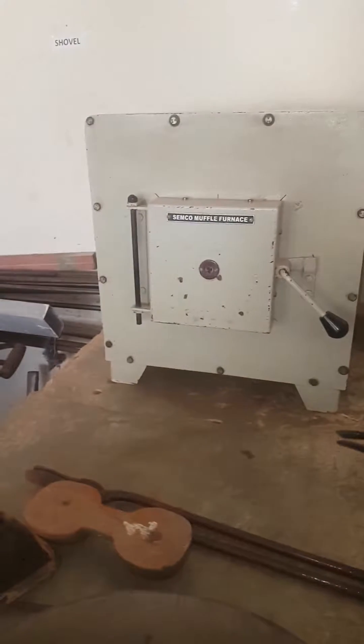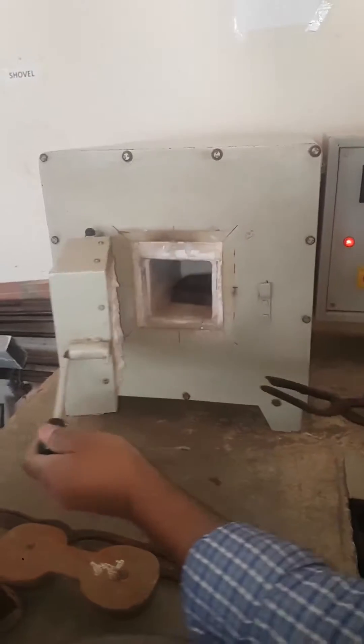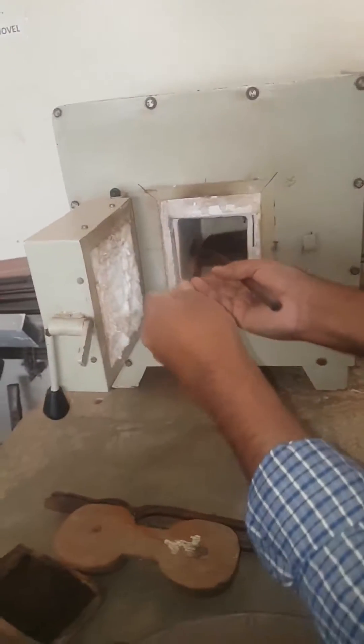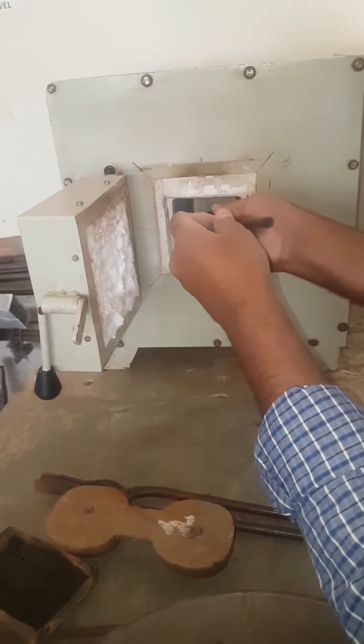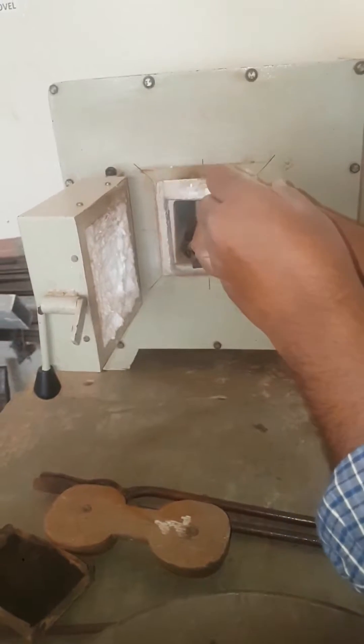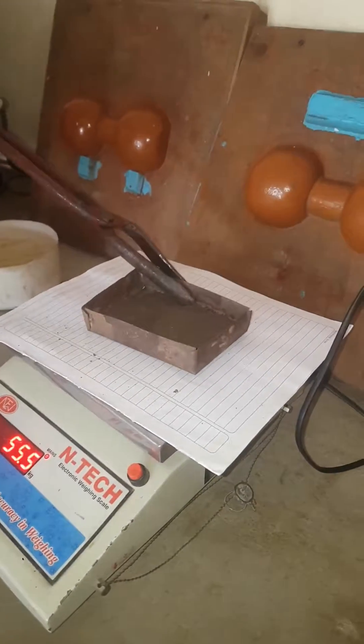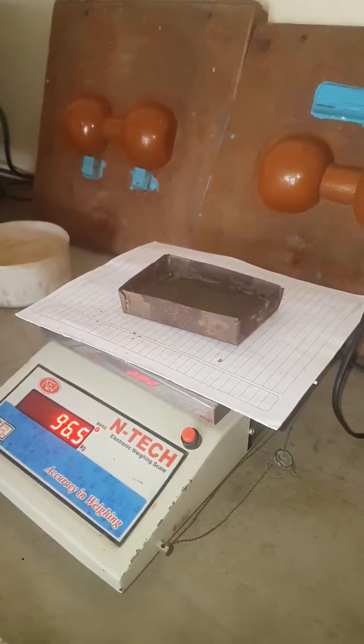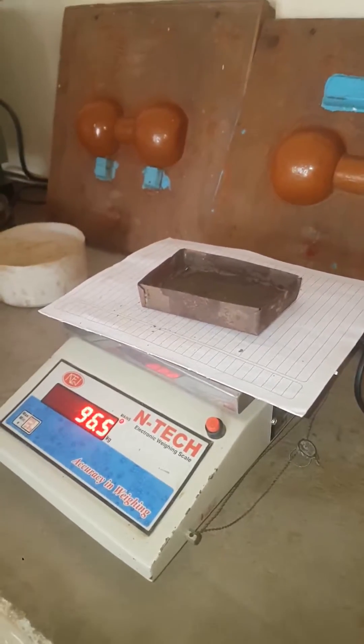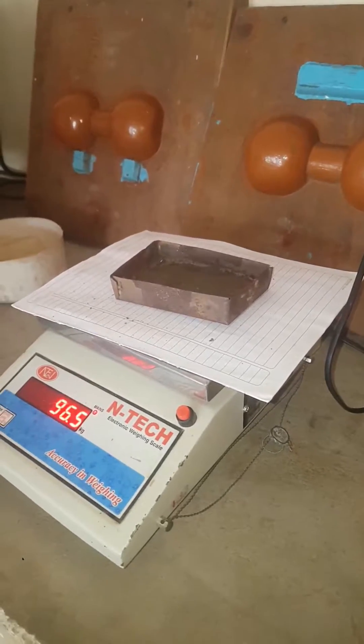After a period of 10 minutes it has been switched off and the sand has been taken out. This will be weighed again and as we can see the weight has reduced — it has come down to 96.5 grams. So from 100 grams it has come down to 96.5.